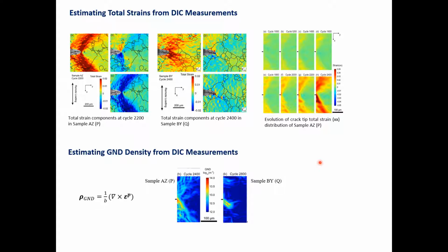So if we make the assumption, which I don't think is too unreasonable, that the DIC strains, being total strains, particularly in the unloaded state, are representative of the plastic strain, because in the unloaded state there is no load, it's purely the residual strains plus the plastic strains. We make the assumption that the residual strains are small, so there's an assumption that's the case.